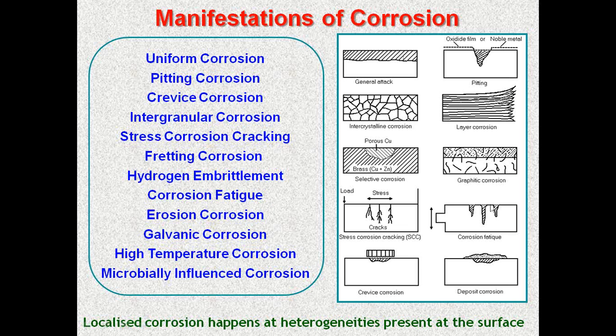All these happen on the surface of the material, and I have given a typical schematic picture of various types of corrosion. And all this happens because of the heterogeneities that are present on the surface. Every metal and alloy will have some heterogeneities, starting from their grain boundaries, the secondary precipitates, the casting defects, the weld defects, and also some stresses or inclusions. Whatever heterogeneity is present on the surface will always provide a site for the corrosion to start.